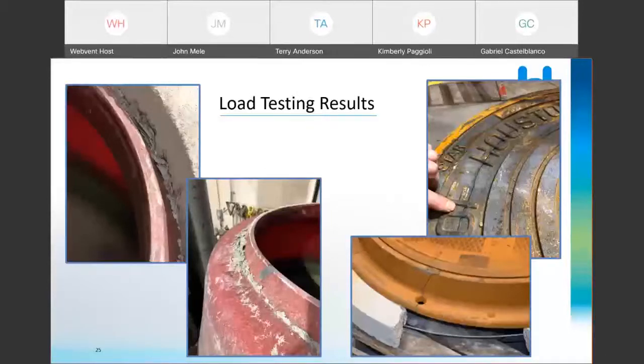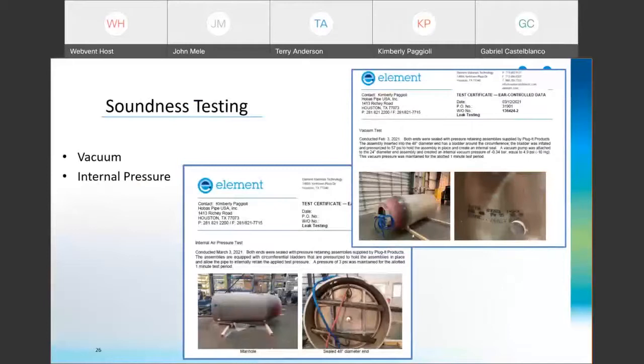The final phase of the testing was to perform an internal pressure and vacuum test to ensure the tested manhole is sound. In both cases of loading the specimen, no damage was found in the structure, and therefore no leaking was found during either the vacuum or the internal pressure test. All of these test reports I've discussed today are available to you upon request.